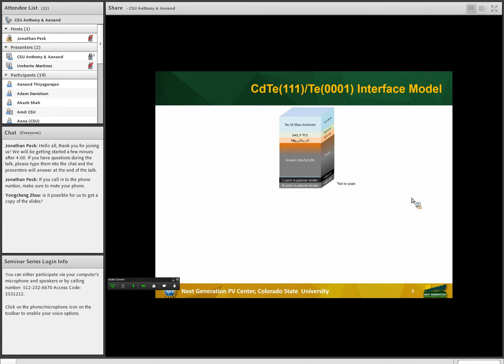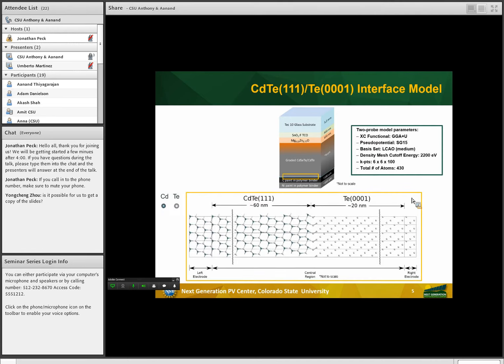The first DFT model simulates the CdTe 111 tellurium interface. We use, as Umberto described in his presentation, a two-probe model that consists of a CdTe left electrode and a tellurium right electrode, as well as a central region that makes up the entire CdTe tellurium interface. This model has a total of 430 atoms, and it must be sufficiently long in order for us to capture the screening region within the central region to ensure modeling convergence. And again, we're using DFT and this model to determine the mechanisms at the CdTe tellurium interface that enhance device performance.